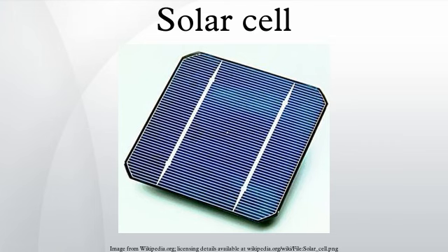The production of a-Si thin film solar cells uses glass as a substrate and deposits a very thin layer of silicon by plasma-enhanced chemical vapor deposition. Protocrystalline silicon with a low volume fraction of nanocrystalline silicon is optimal for high open circuit voltage. nc-Si has about the same band gap as c-Si, and nc-Si and a-Si can advantageously be combined in thin layers, creating a layered cell called a tandem cell.